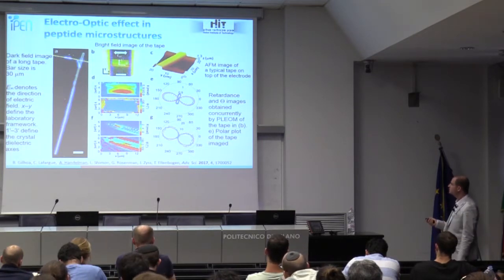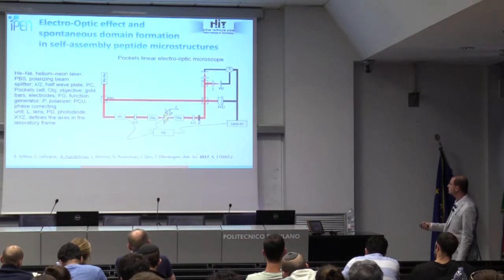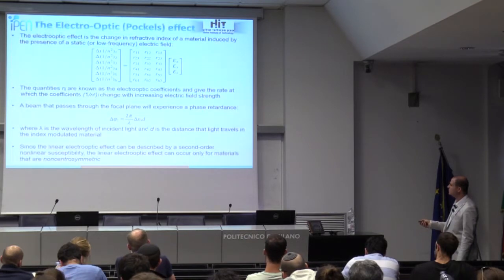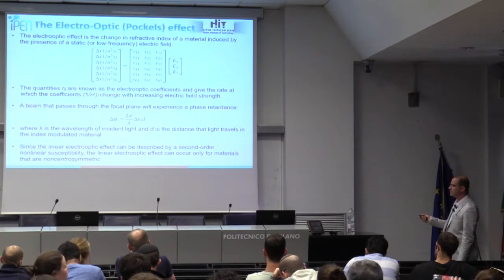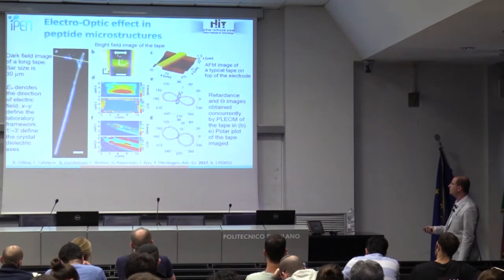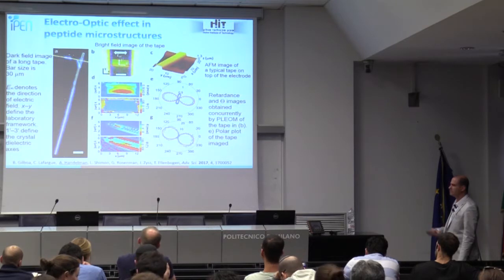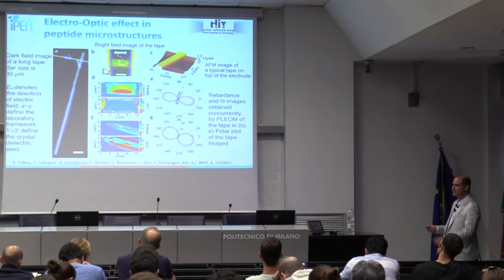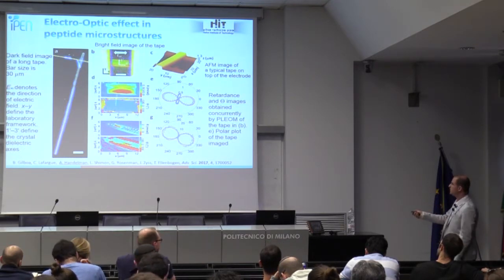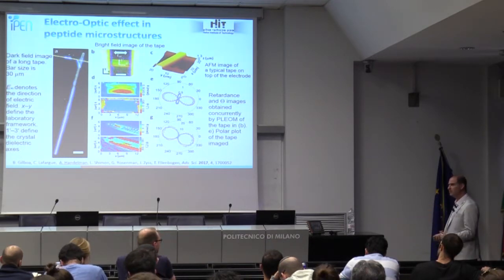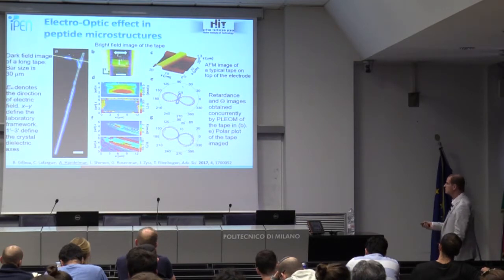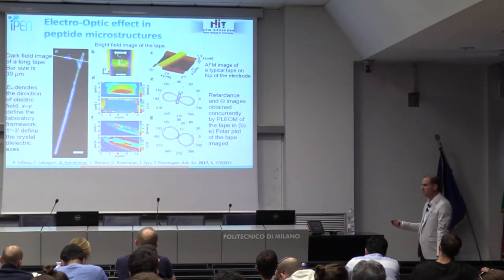We can get the amplitude and the phase. The amplitude is related to the phase difference that was here. Okay. So we want to characterize the delta n or this kind of tensors. Okay, and the phase is related to the polarization. So the Pockels cell is to translate the amplitude to the difference in the phases. So this is why we need the Pockels cells.